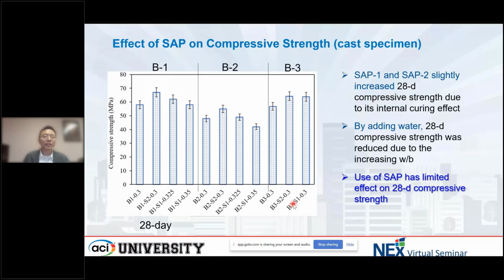First, this slide shows the result of the cast sample. When we add SAP without additional water, it increases the strength, not very significantly actually, around 10%, because of its internal curing effect. As the water-binder ratio becomes higher, there is a little bit of reduction. Overall, the compressive strength of the mixture made without SAP and with SAP are very similar.